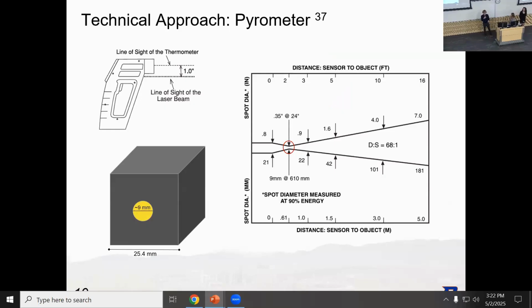Now getting into the pyrometer that Lauren started to discuss, in order to measure the radiated heat or the surface temperature of our sample, there are some things we need to take into account. Something nice about our pyrometer is it had a laser sight, so we can make sure we're looking at the same point every time between all of our measurements. Something else we need to take into account is the spot size. The spot size is essentially what our pyrometer is looking at, and we want to make sure that we're looking right at the graphite. For us, we want the minimum spot size, so that if there's any bumping of the pyrometer or some movement within the sample, we're still looking at the graphite. So we purposely distance our sensor 61 centimeters away in order to get that minimum 9mm spot size.